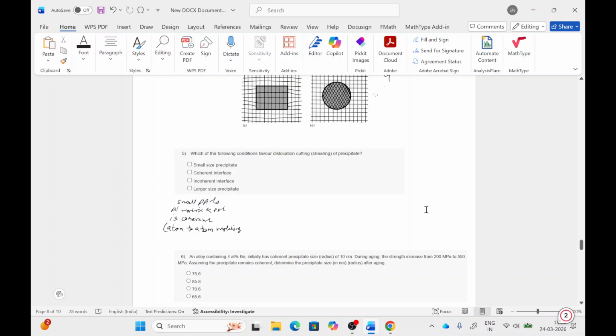So now we can solve this fifth question, which is asking what conditions favor dislocation cutting of precipitate. Dislocation cutting will only happen when a coherent interface is present between precipitate and the aluminum matrix, and when the precipitate size is small. So the first and second options will be correct for this. Is it clear?